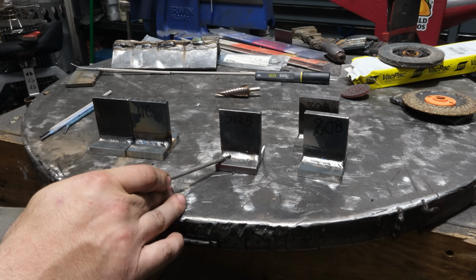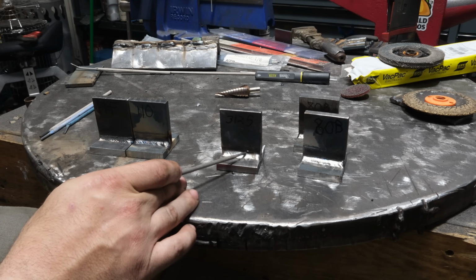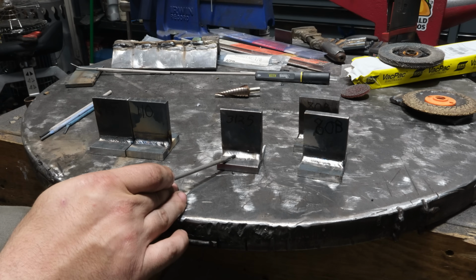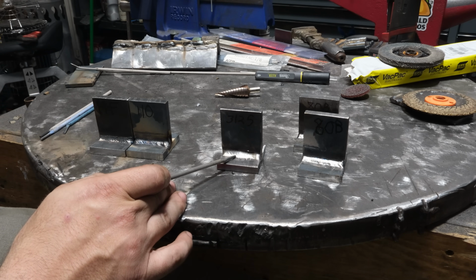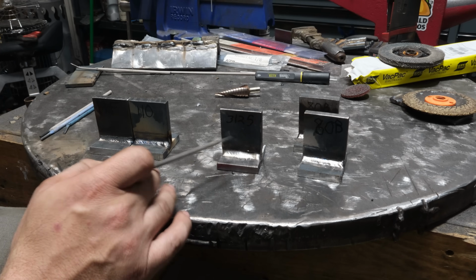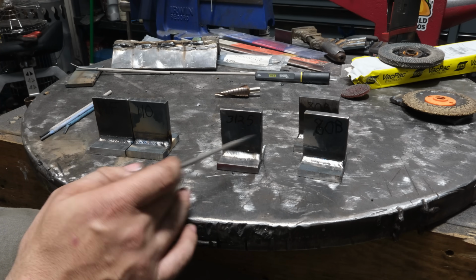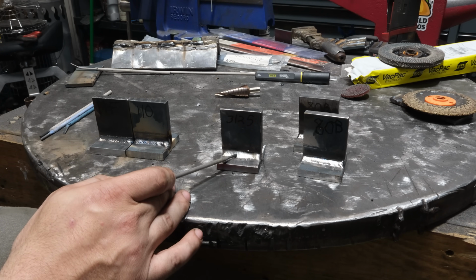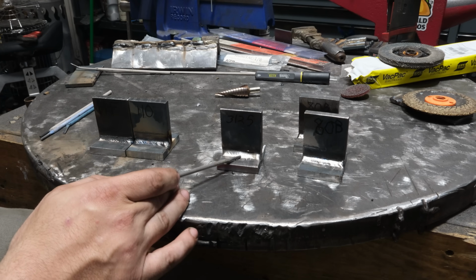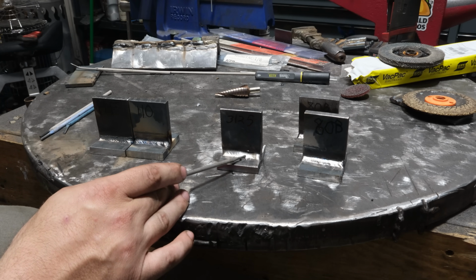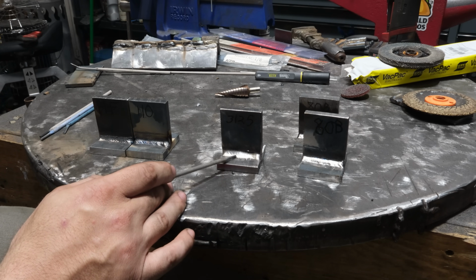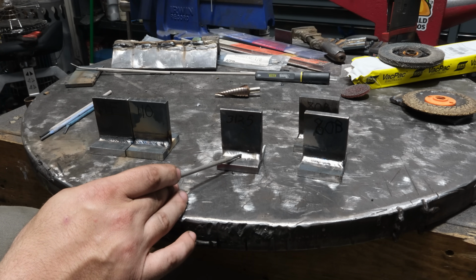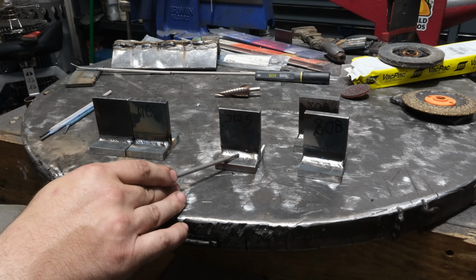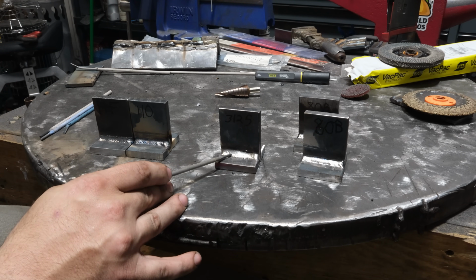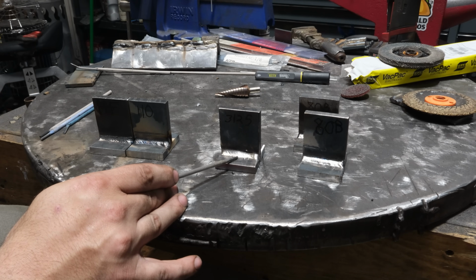Now this 312 stainless produces a very wide flat weld, and I was cramming a rod in there and it's still difficult to control the arc, and that's typical with the 312 stainless. I use it mainly as a repair rod, and the quality of the first pass of the weld is of little concern, I guess, because I normally use it on things like cast iron and spring steel, etc. So you're welding on stuff that doesn't weld good anyways.